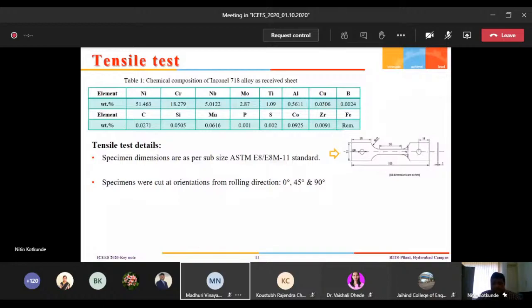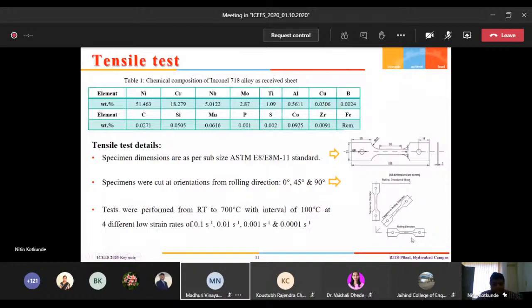Like this, if you see the schematic, this is the rolling direction, this is diagonal to the rolling direction, and this is the transverse direction, to understand the material property variation at different directions. And then we tested it at different temperatures and strain rates.